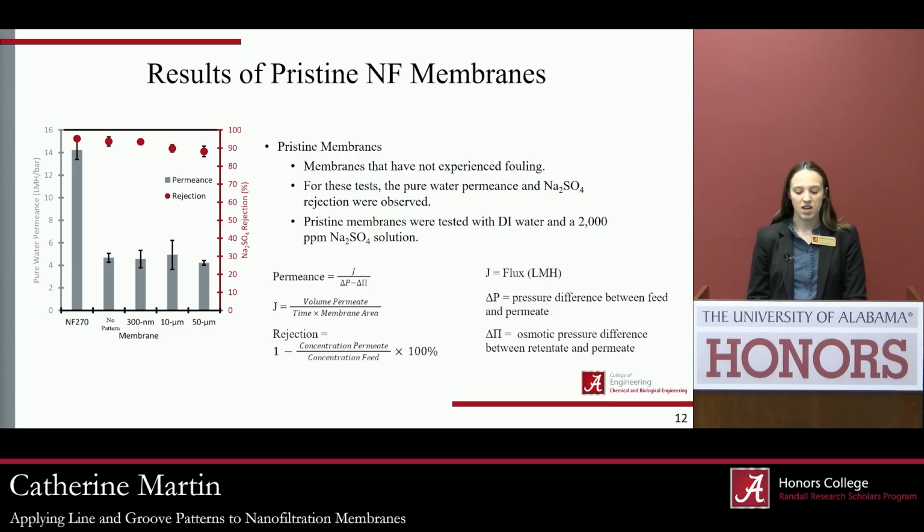These tests demonstrated that the membranes we fabricated had a slightly lower pure water permeance than that of the NF270 purchased membrane, but we saw no significant statistical differences between our in-house synthesized membranes and the purchased membrane for the rejections. Another thing that we saw from this test was that for the synthesized membranes, we saw no statistical difference in the rejection or the pure water permeance based on the patterning. The patterning did not influence that for our synthesized membranes.